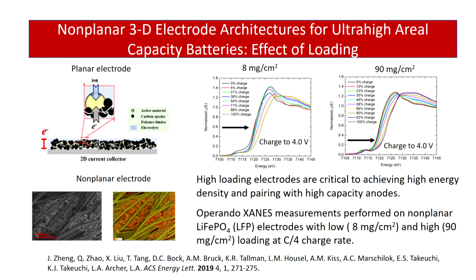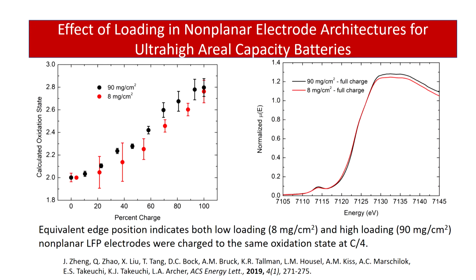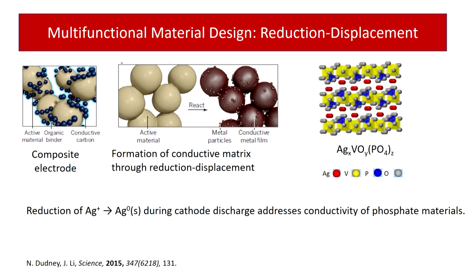So this is an example, a project that we did with Lyndon Archer at Cornell, looking at non-planar electrodes that have very high areal loading in terms of being able to achieve effective utilization. We tracked these areal loadings by XAS again, and found that the utilization of very high loading and moderate loading is very similar as long as we have these three-dimensional electrodes that have high ion access as well as high electrical connection within the electrode itself.